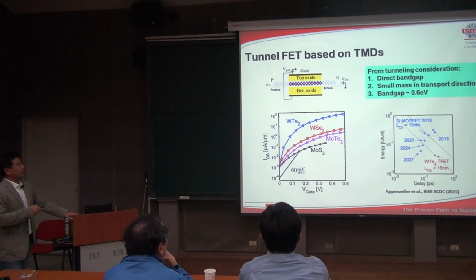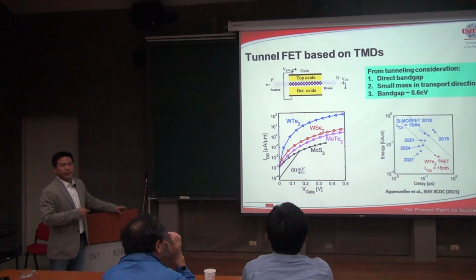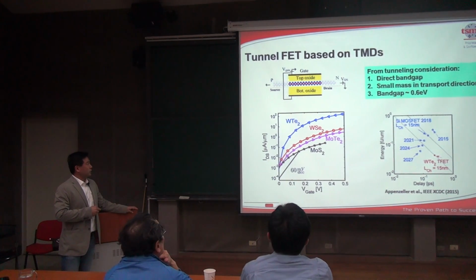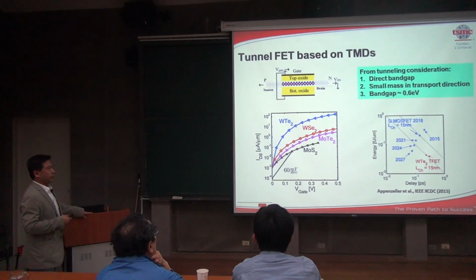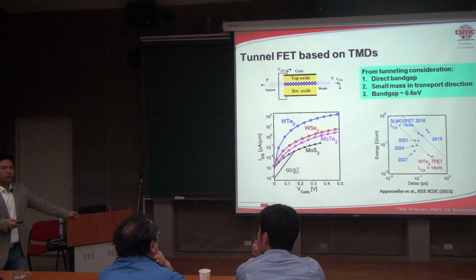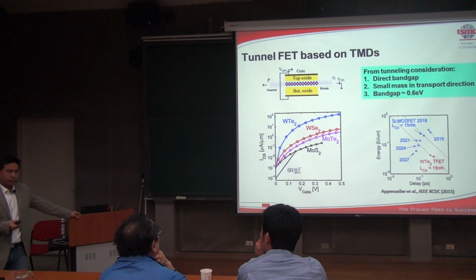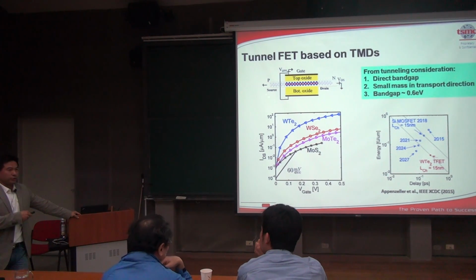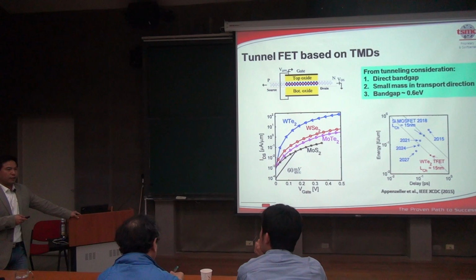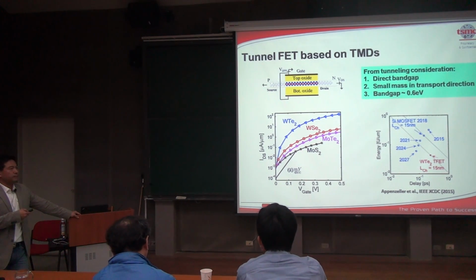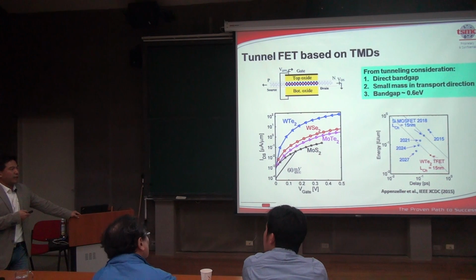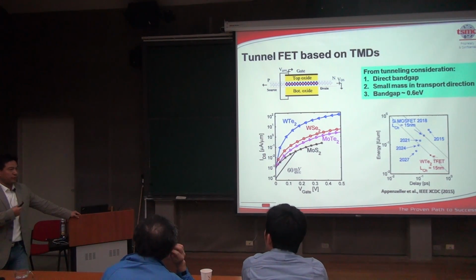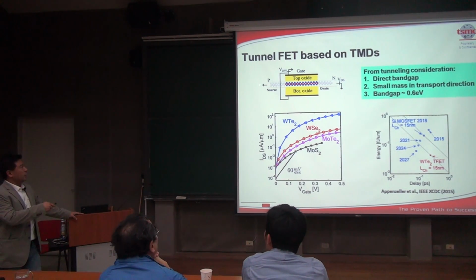Like this, you need it for the FET. Eventually, you have to dope the device, dope the channel. As you are probably aware from the literature, there are known techniques to dope the material by charge transfer with some physical molecules that either have a higher electron affinity or lone electron pairs that could transfer charges to the 2D materials. That has been shown by many groups. For example, in one extreme case, potassium atoms would heavily dope these 2D materials into N-type because they like to give away electrons, and they sit physically on the surface of the 2D material.